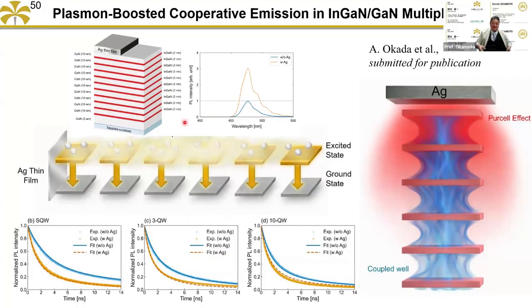Then, through some theoretical analysis, we found that each layer was synchronized with each other. That's why the lifetime increased with increasing layer number. And in this region, if it's synchronized with each other, that's why even the surface plasmon enhances the one layer.